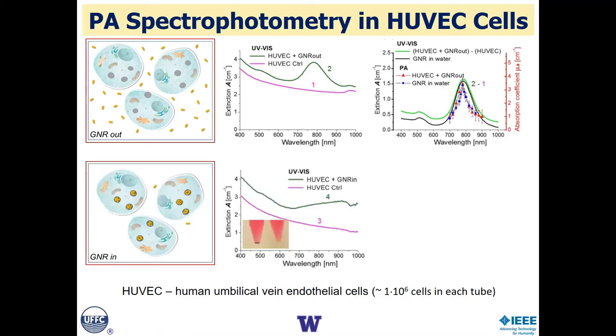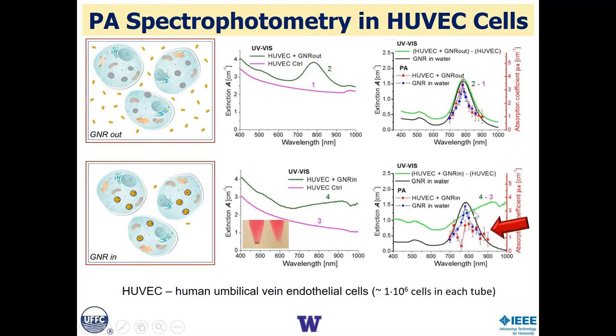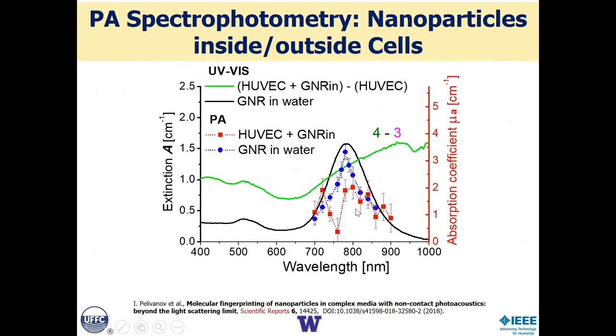What happens now when these nanoparticles start to traffic? In particular, what happens when the vast majority of the nanoparticles have been captured inside cells and are at high densities inside the cells, this very strong optical environment? When I make the optical extinction measurement, I get garbage, this spectrum here. However, the photoacoustic spectrum is very interesting. Let's look at that in more detail. So here's this non-contact photoacoustic measurement. This is the garbage UV-vis measurement.